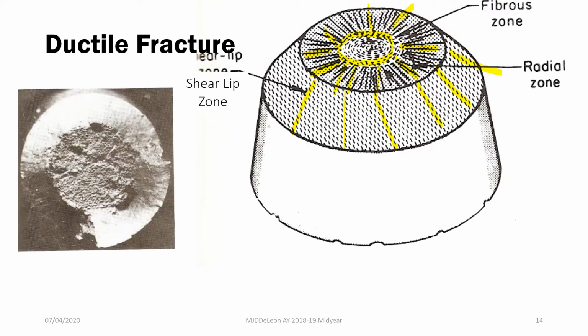And shown here, sa kaliwa, this is a fractograph of your ductile fracture. Makita natin dito sa fibrous zone mo and sa radial zone, here, sa fibrous zone, medyo rough ang surface mo, then once you go outwards, smooth na yung fracture mo. So pag meron kang rough surface, usually, this is a characteristic of a ductile fracture because allowed yung crack mo propagate transgranularly, intergranularly, or in the grain boundaries.